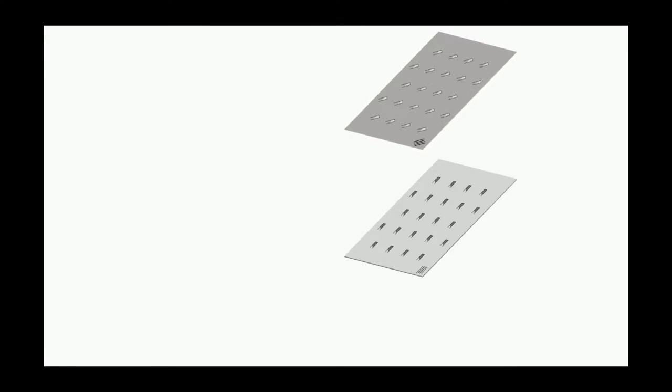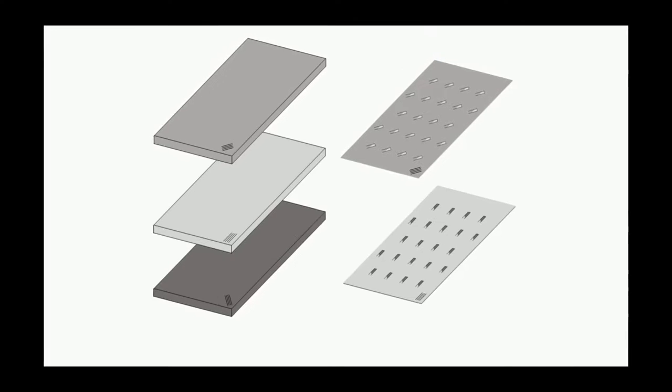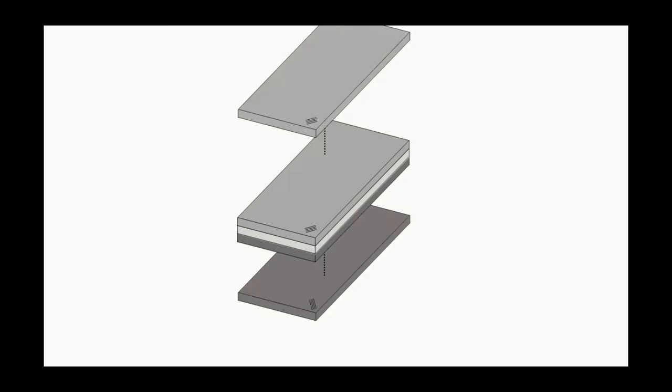The fiber orientations of each unit are chosen to match the adjacent composite layers in the final layup. So the orientation of the top layer of the reinforcement unit is chosen to match that of the layer that will be above it in the final layup, and the orientation of the lower ply in each unit is chosen to match that of the ply that will be below it in the final layup. Once all the reinforcement units have been manufactured, we then conduct a regular layup process where we insert the reinforcement units at the appropriate locations within the laminate.